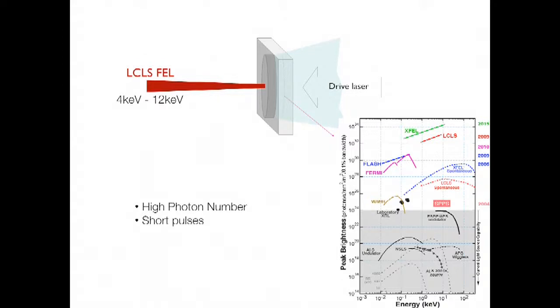So for LCLS, we need the very short pulses for these experiments. We need the high photon numbers. A lot of the probes we use are fairly photon hungry. Sometimes we even just use LCLS itself to create this material. If we focus our beam to very small spot sizes, we can create temperatures high enough to be in these regimes. But most of our experiments use other lasers, drive lasers that create either the high temperatures or the high pressures by heating it or by driving shock waves or using relativistic particles we create to get us into this regime.